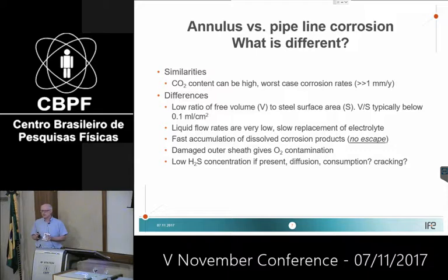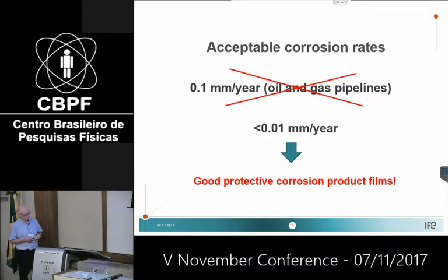You cannot produce forever. For a while, you will produce, it will dissolve, you reach saturation, you reach supersaturation, it starts to precipitate, it forms protective layers on the steel. That's actually the reason why it survives, but you don't form it always. So that is very challenging. And if you have H2S coming or diffusing also into annulus, then we come into this situation: will the H2S build up, or will it be consumed and kept at a low level? And if it builds up, cracking, of course, becomes a very big issue. I'll talk a little about that.